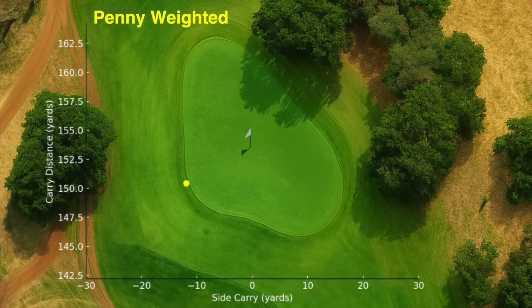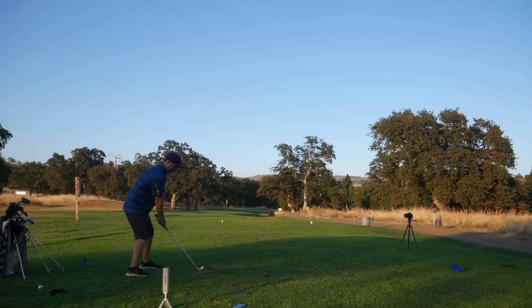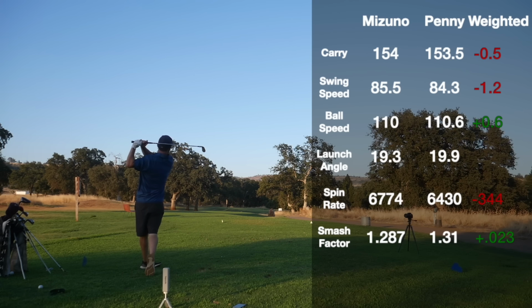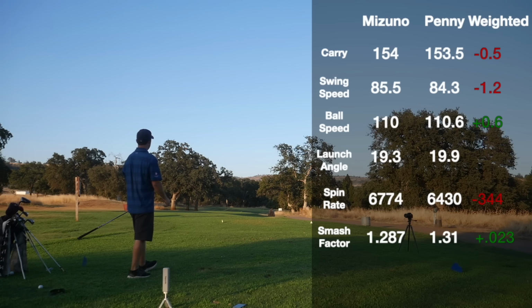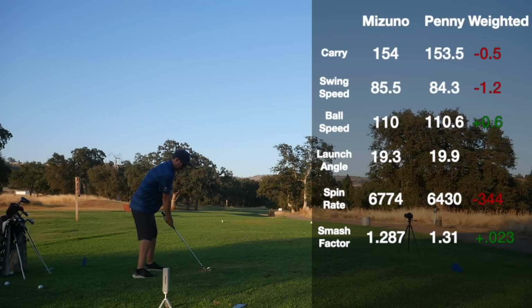With the penny iron weighted, Packard's dispersion definitely tightened up, which was really interesting to see, and it's obvious when we compare it to the previous data of the unweighted penny iron. The dispersion now matched pretty close to the Mizuno overall. It's also really fascinating that Packard's metrics with the weighted penny iron were almost identical to the Mizuno, except that the spin rate was down 344 RPMs, which, like I said, could be due to a number of factors, potentially because of the metal that we used. He was hitting the weighted penny iron really well, with a smash factor over 1.3, which is insanely good.